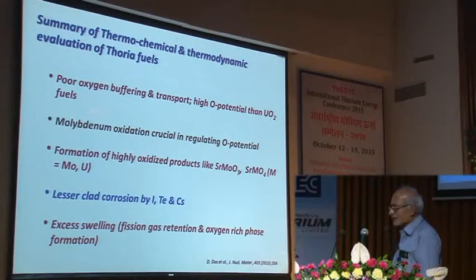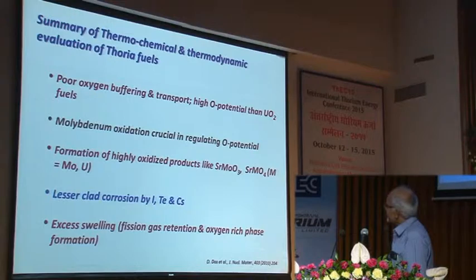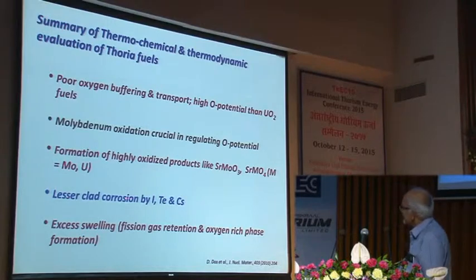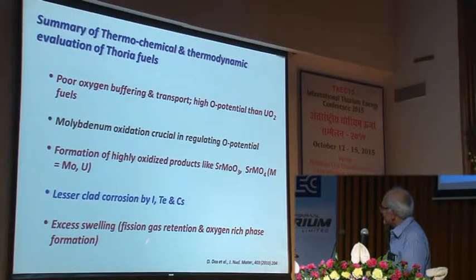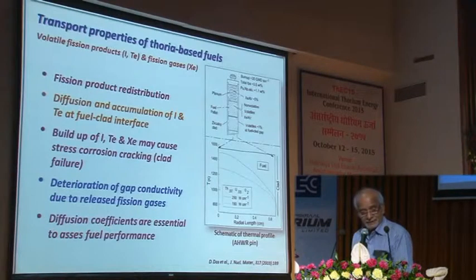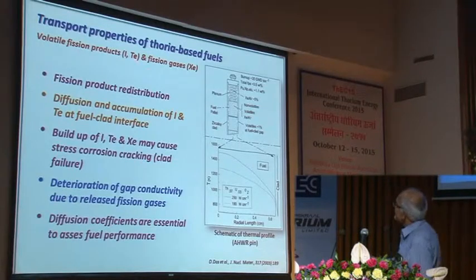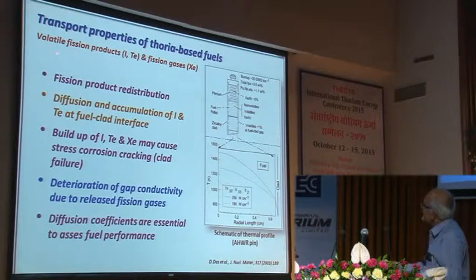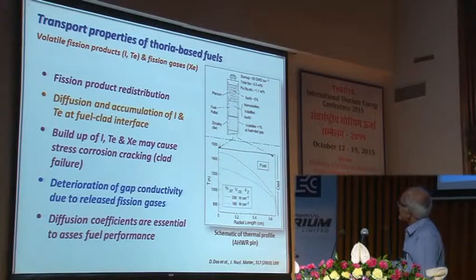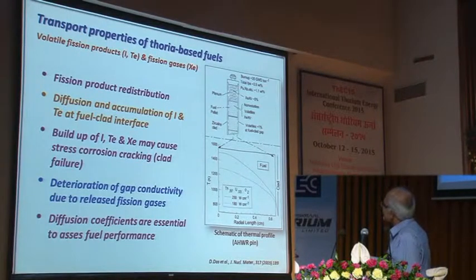The molybdenum oxidation, which was referred to by Dr. Ramkumar, is crucial in regulating oxygen potential. There is formation of highly oxidized products like strontium molybdate, and so on. There is lesser clad corrosion by iodine, tellurium, and cesium, and excessive swelling, that is, fission gas retention and oxygen-rich phase formation. The transport properties of the thoria fuels, in particular for the volatile fission products iodine, tellurium, and fission gas, that is xenon, determine how these get distributed.